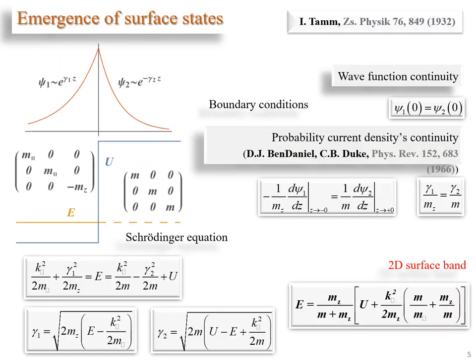Such surface electron states were predicted by Tamm as early as 1932. Here we present the simplest model explaining their existence at the (1,1,1) surface of the noble metals with rectangular potential barrier in the effective mass representation. Periodic potential inside the crystal is converted into the effective mass tensor. In this case, usual boundary condition for wave function derivatives should be replaced by the so-called band bending boundary condition. We see that surface band exists if the effective mass in the z-direction, normal to the boundary, has different signs on the sides of the boundary, as is the case for the (1,1,1) noble metal surface.